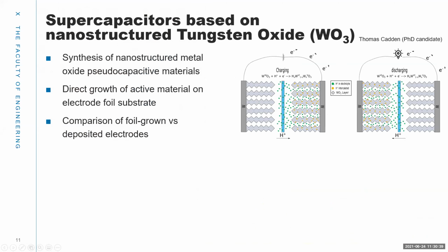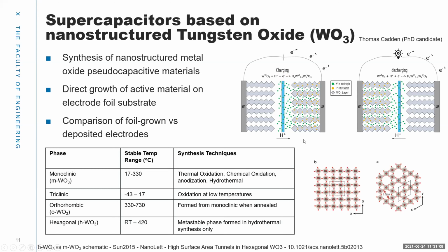Finally, because this session is all about materials, I wanted to talk about one of my PhD students' projects, which is developing nanostructured tungsten oxide materials for supercapacitors. And tungsten oxide has some really interesting redox properties. It has quite fast proton intercalation kinetics with an electron reduction step to form this tungsten bronze material. And it comes in several different crystal polymorphs. So the most active for this reversible reduction and oxidation mechanism is found to be this metastable hexagonal phase. And so the challenge is to synthesize high surface area tungsten oxide with this hexagonal phase reliably and reproducibly and in enough quantity to make an energy storage electrode.